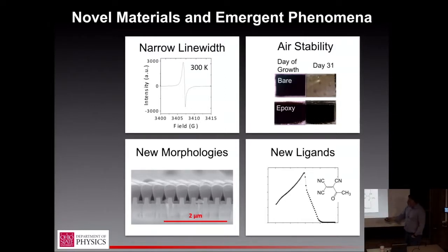And then very recently, so this is all published work that I'll put up the references at the end of the talk, but very recently we've also discovered these new morphologies. For example, when we grow on SiO2 substrates that have been nanopatterned to have these ridges, rather than getting a conformal folded sheet, we actually get these nanowires. And so this makes for great SEM images. Beyond that, it turns out that these structures introduce exactly the in-plane magnetic anisotropy that we've been looking for.